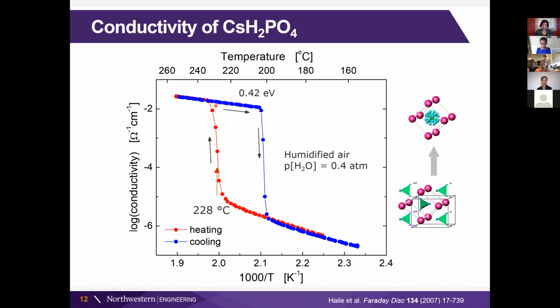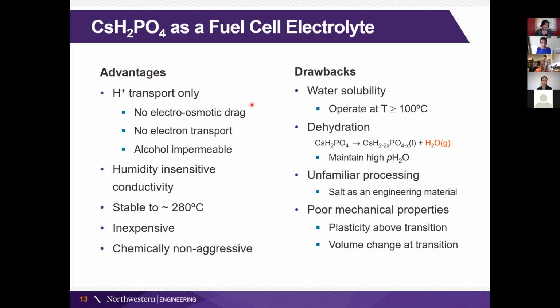So we have this dramatic increase in conductivity as we go through the transition from the ordered monoclinic to the disordered cubic phase, yet it is still solid, crystalline. You take a diffraction pattern of this, and it's a very sharply crystalline material, and it has this very high conductivity. So using it as a fuel cell electrolyte, it has some advantages and, of course, some disadvantages.